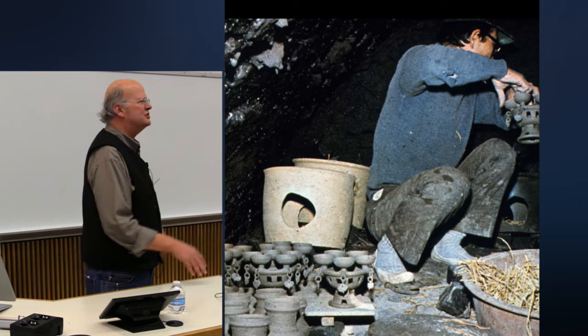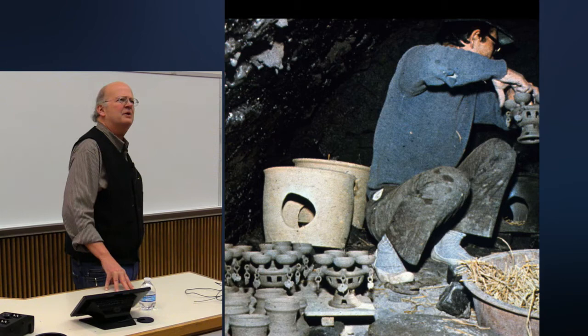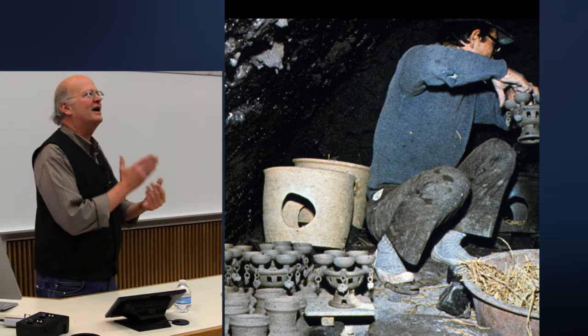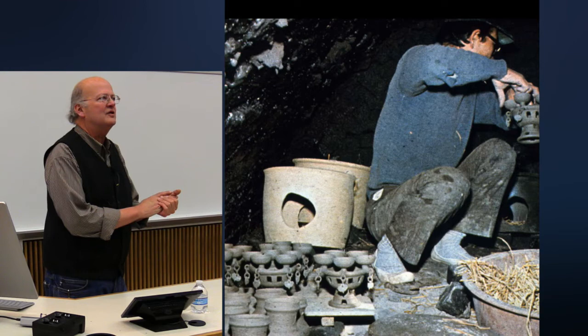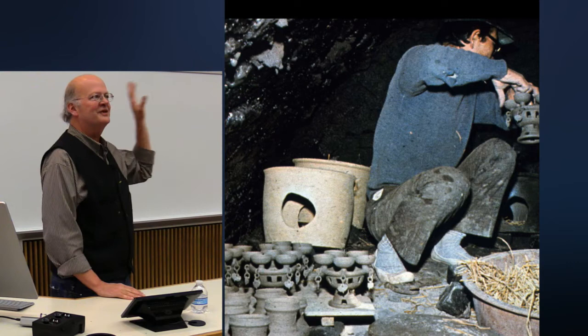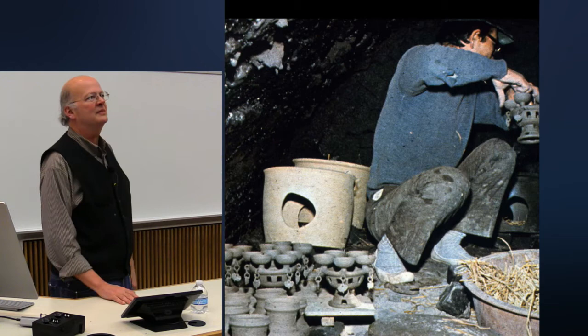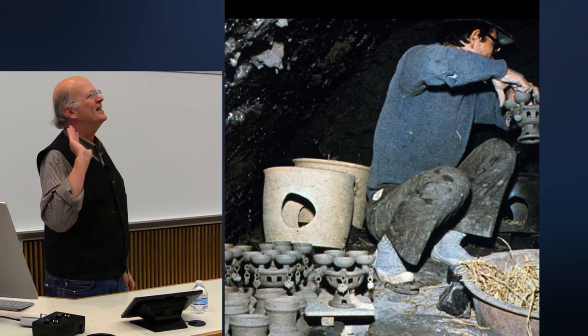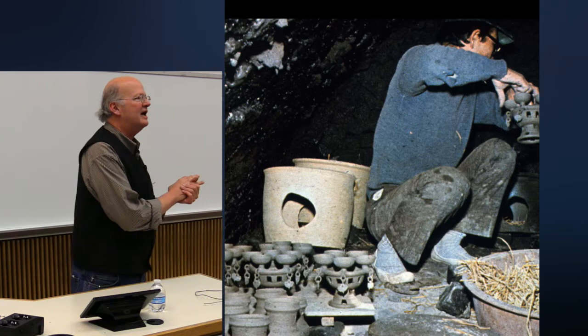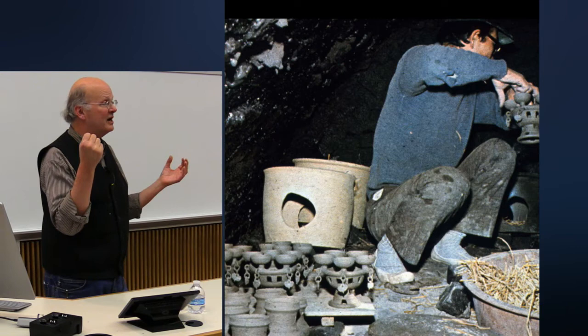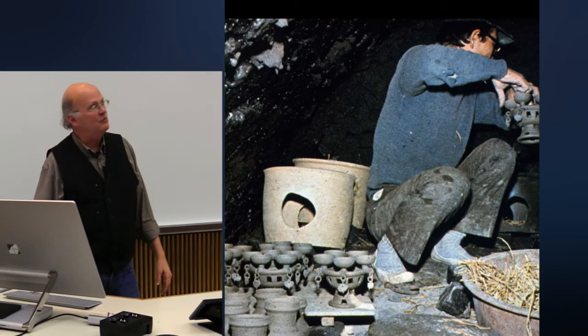I used to use cast iron pans as the example of black iron oxide, but I'm not so sure that they're so common anymore. But anyway, iron, when oxygen is taken away from it, you can go through three states: red iron oxide, black iron oxide, metallic iron. There's actually a few others in there too, but you can get a chemistry teacher to explain that. What had happened was there is iron in this clay that they were using in Korea, and by putting excess fuel into the kiln, they'd stolen oxygen away from the red iron oxide that was in the clay, and turned it to black iron oxide. So these pots that we saw were colored by black iron oxide.